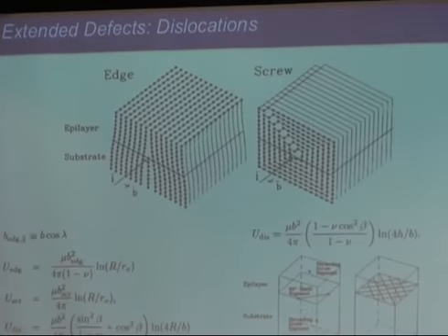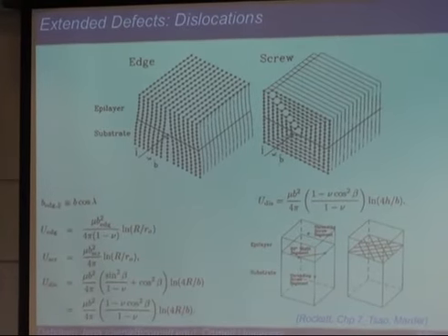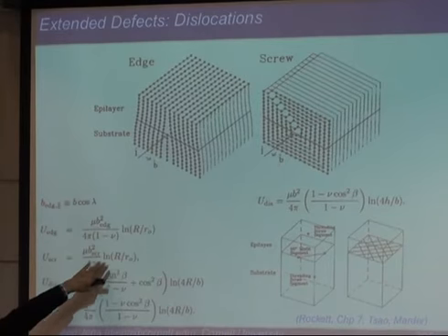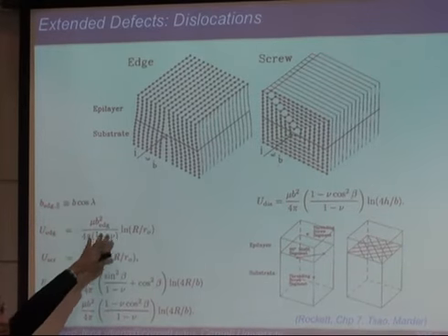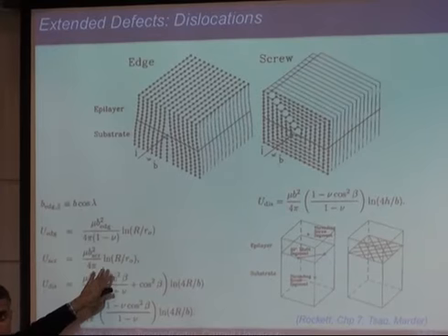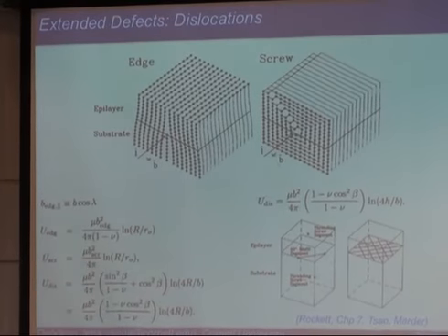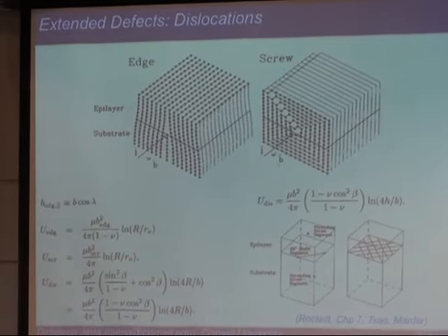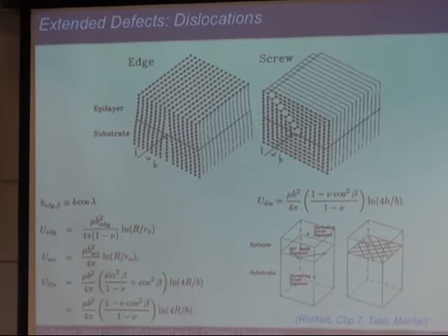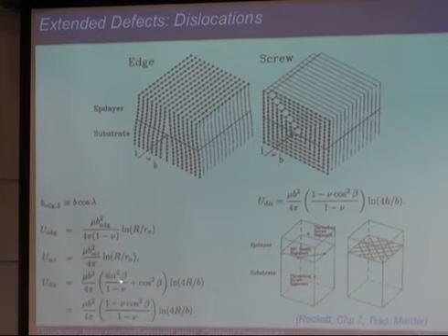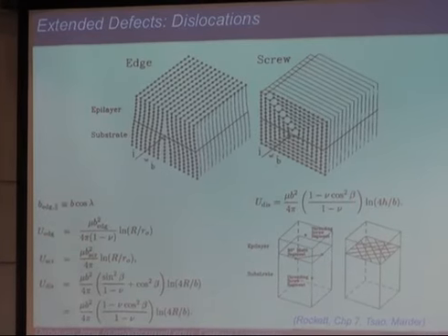So you'll form some dislocations. I forgot to mention a little change here: this is the edge dislocation energy cost. Similarly, you can have a screw dislocation energy cost, and because there's not much strain in a screw dislocation, there's no Poisson ratio. None of that appears here. They're all gone. So the screw dislocation is unstrained, and everything else remains pretty much similar. Sometimes you can have dislocations where the Burgers vector may not be completely perpendicular to the line of the dislocation. It can be at an angle, in which case you'll have this cosine squared, sine squared theta. I'm not getting into all the details of that right now.